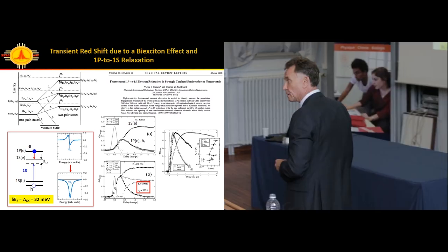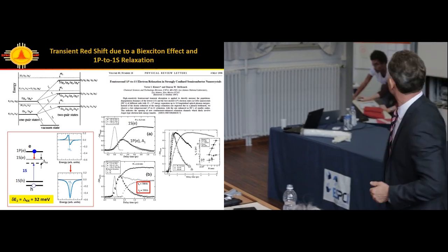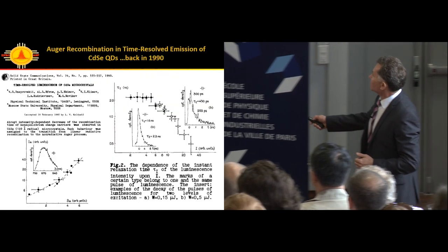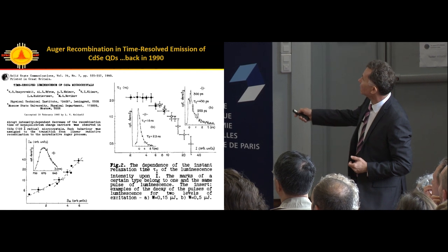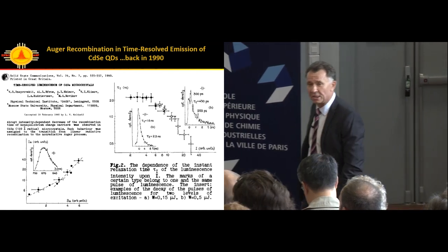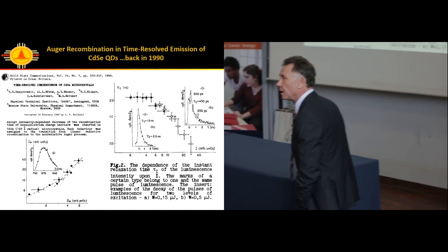It's just getting faster. Obviously it was not phonon-mediated relaxation. That was the conclusion. Relaxation dominated by electron-hole energy transfer. New phenomenon enabled by extreme quantum confinement. Cool stuff. Back to this paper, 1990, my first study of Auger recombination in nanocrystals.